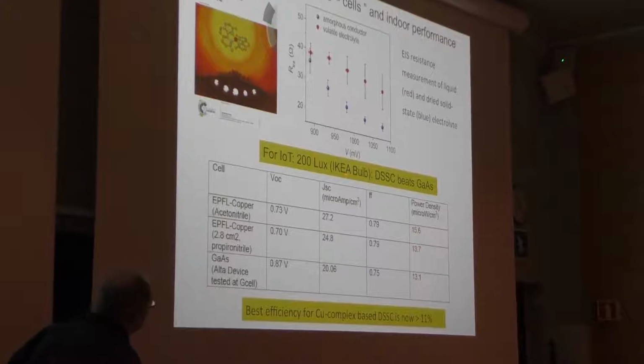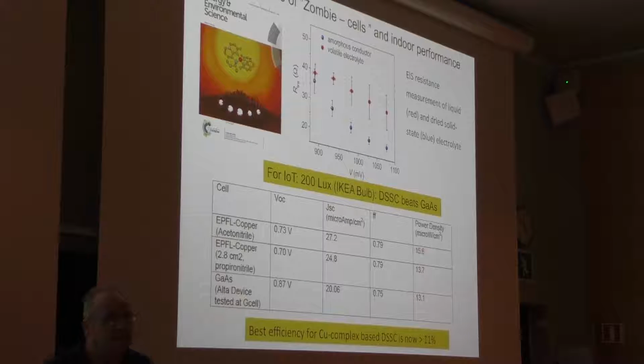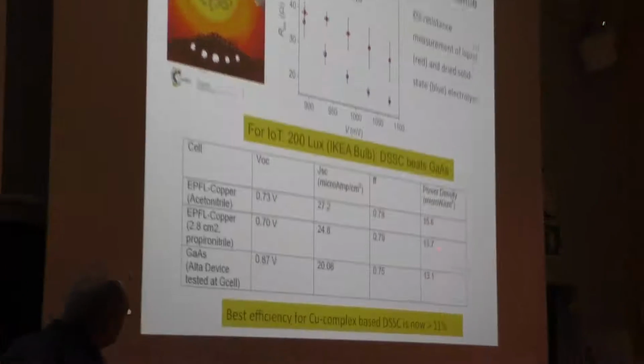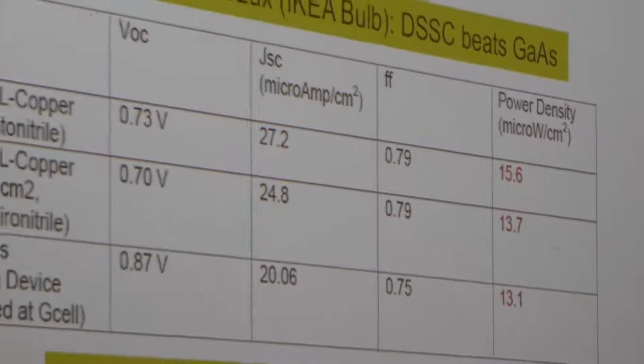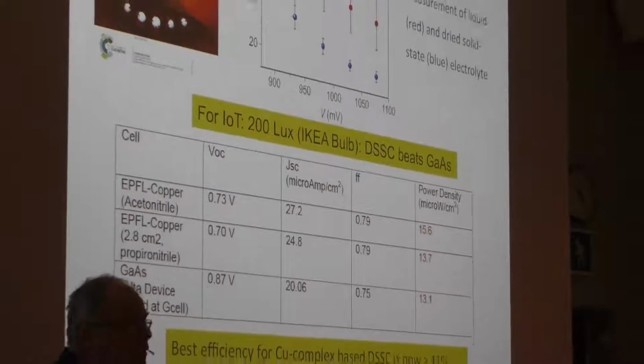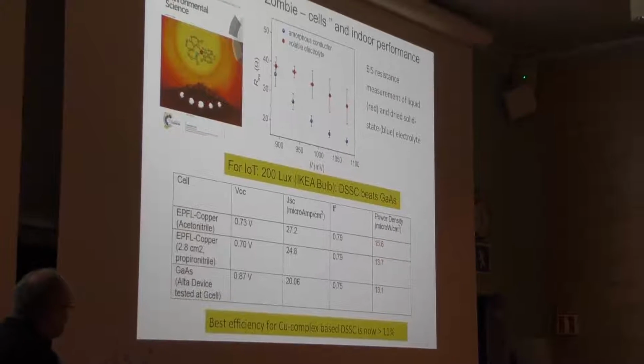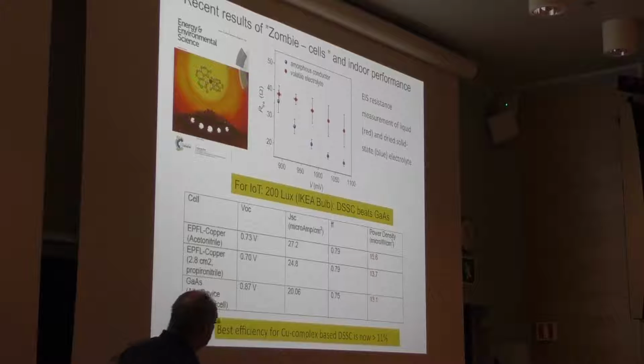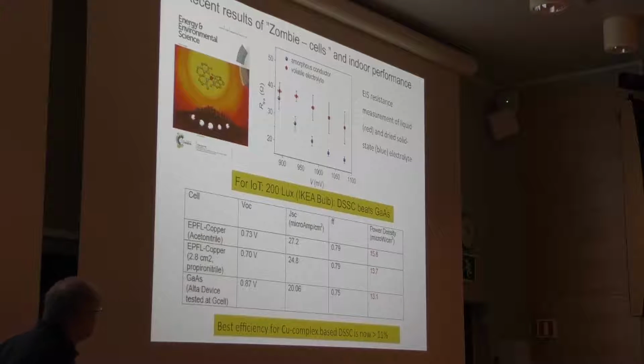This is unpublished, but we also measured for indoor application. Of course, as a Swede, we take a light source from IKEA, 200 lux, so this is like we have in here. And the comparison is interesting. We have our copper dye-sensitized cell giving at this 200 lux about 15 microwatt per square centimeter. And it's actually, this is the champion, I should say, but it's actually higher than gallium arsenide solar cells, and that I think is quite interesting. So gallium arsenide is of course the very, very best solar cell with 29% in sunlight, let's say. But in indoor here, because we can match the lamp spectrum and so on, dye sensitized cells are really competitive. So maybe it's at least as good as gallium arsenide for indoor applications.